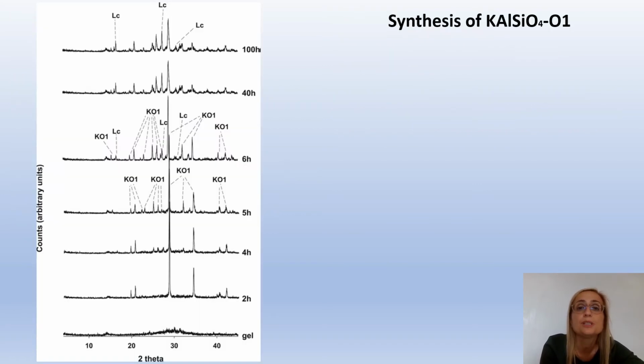The mixture was heated inside the autoclaves at 150 degrees Celsius and ambient pressure for a duration of 1 hour. Characterization by diffractometric analysis showed the resulting material to be amorphous, as is visible from the figure. The gel precursor was then calcined at 1000 degrees Celsius and sampled at scheduled interval times.